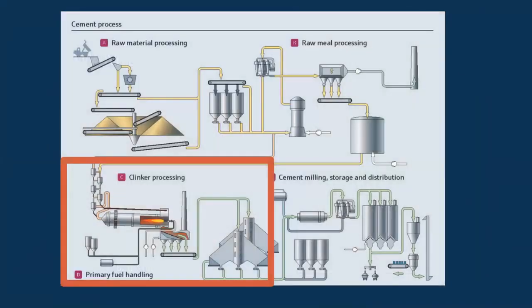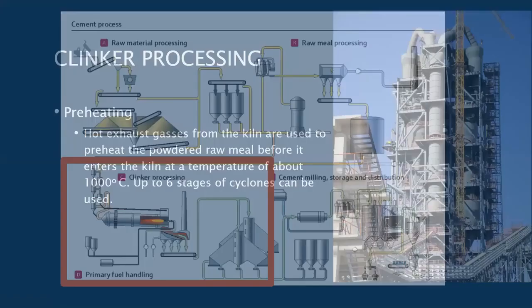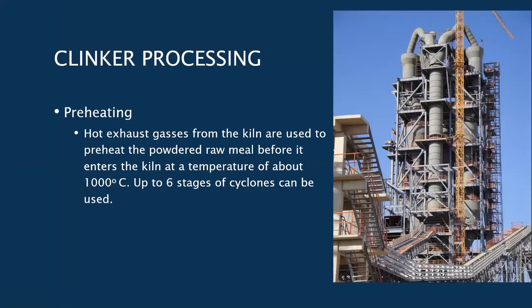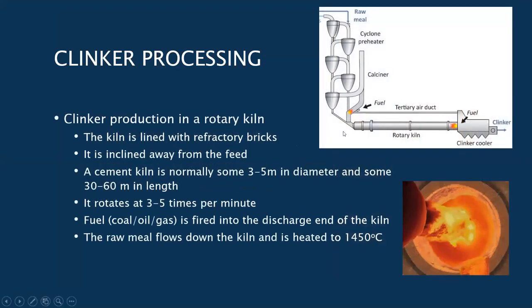Clinker processing, now is when the cooking process starts. First of all, we have this preheating. Now, when I joined the industry, there was nothing like a preheater. Today, these preheaters are used to gather what used to be waste heat and use this waste heat to heat up the fine powder to about 1,000 degrees, even before it enters into the oven, which is the kiln. The kiln is this part at the bottom over here, and there's the preheater. So the powder comes down here and is heated up to about 1,000 degrees before it enters the pipe or tube, which is the kiln.